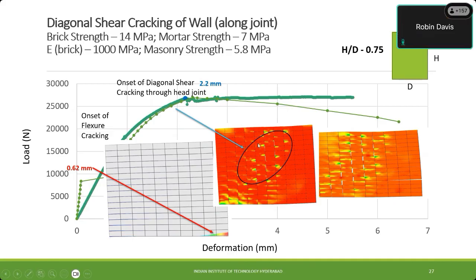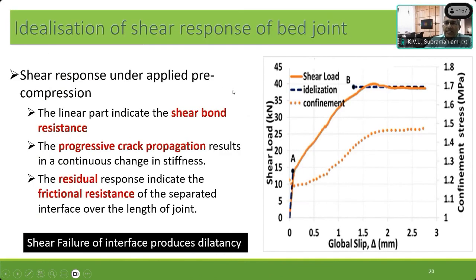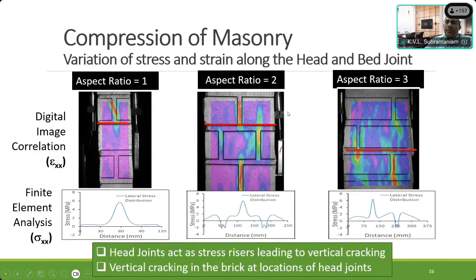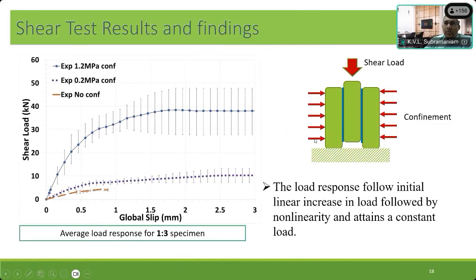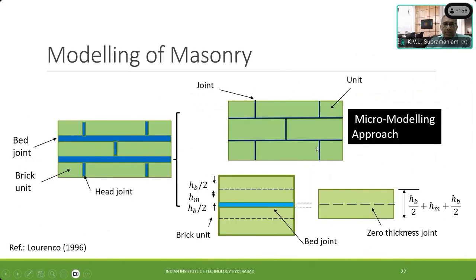Just thinking that you did that on small specimens, and then you could locate where the first crack appears. That we could do. At the material level, of course, we had very nice control on the whole thing. So we were precisely able to locate where the cracks were forming. Very interesting. So this then led to the material model, which was then fed into a finite element model. Let me show you the model.